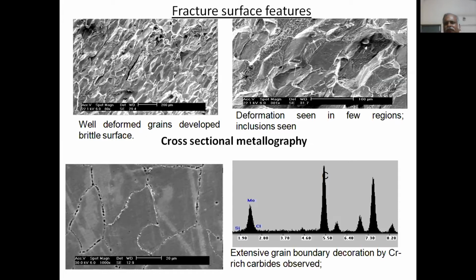Okay, I also mentioned fractography and cross-sectional metallography. Beneath you have two pictures. They exhibit the cross-sectional metallography. What is cross-section? Very close to the fracture surface, slice it, polish it, etch it, like what you do in your metallography laboratory. You will see under the microscope beautiful grains, and the grains are decorated along the grain boundary with a lot of precipitation. What is that?